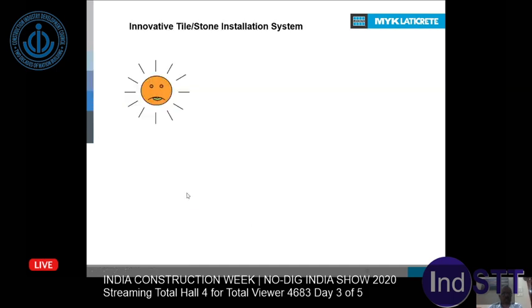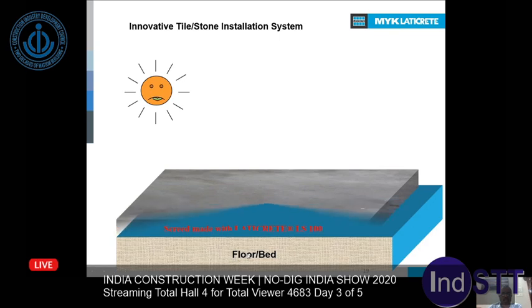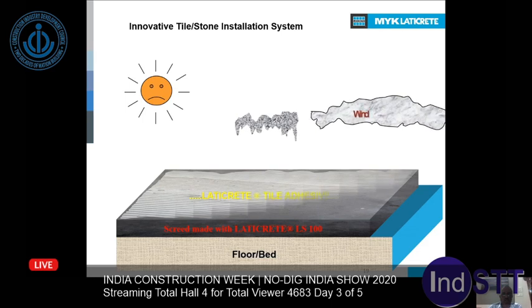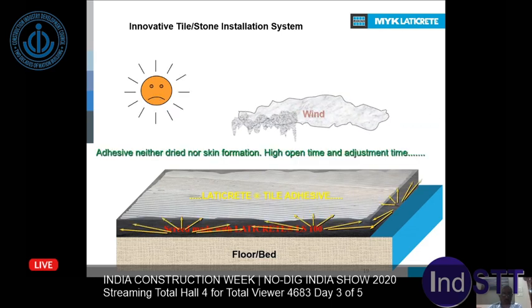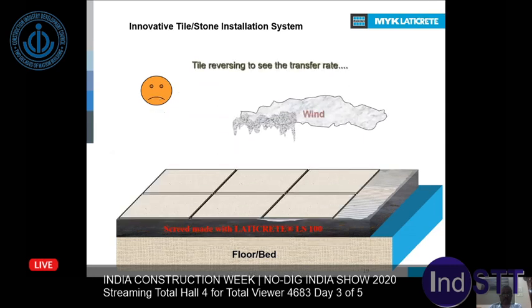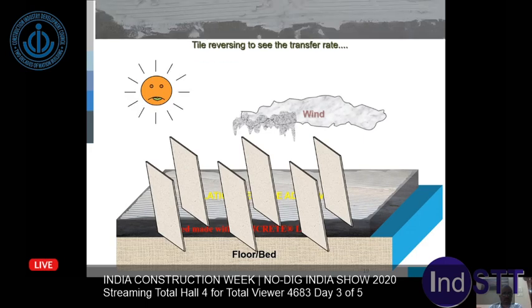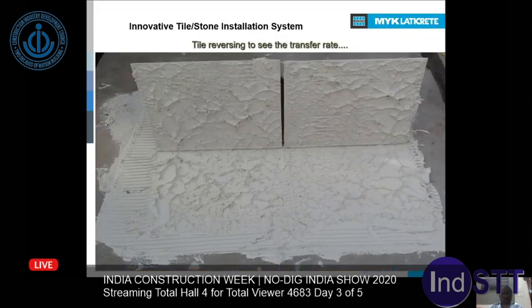And again, going to pictorial, to repeat this, it's a floor bed, concrete, let us say RCC. Then over which we have a screed. That is again a factory made screed. It is not just a sand cement that what we see in the other picture. So this is again allowed to cure for 7 days. So that means it's a very solid, uniform screed material you have over it. Then over which you are putting your tile adhesive, which we talked about. So spread it in a very thin layer. Then you put your tile and grout it with a good grouting material. Then once you flip it, you can see that uniform coverage. There is no gap. There is no area with more material and another area with no material. It's very uniform and adhesion to both tile as well as your concrete floor.